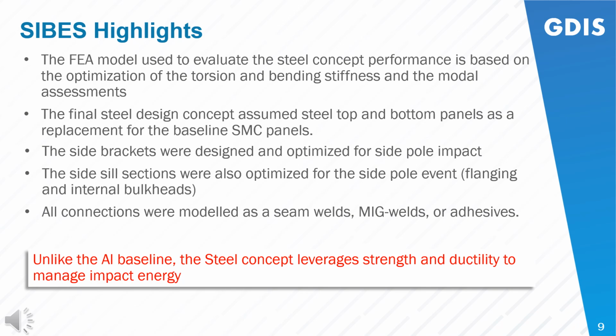The discrete side brackets were designed and optimized for side pole impact. The side sill section also was optimized for side pole impact, both from a flanging and internal bulkhead perspective. All connections were modeled as seam welds, MIG welds, or adhesives. Worth noting here, the big difference really is, instead of just relying on intrusion prevention as perhaps in the aluminum baseline, the steel concept leverages strength and ductility to also manage the impact energy.